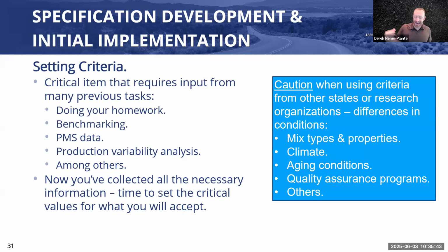That you could look at, someone says X state has a minimum CT index of 100. Well, I have 10 questions to follow that up to get any meaning from that. Is that lab produced or is that plant produced? Was that based upon lab samples or plant samples, right? Okay, how was that validated necessarily, right? If they're doing it in production environment, is that specification based on an average lot? Is that a single test? Is it a statistical spec, etc.?